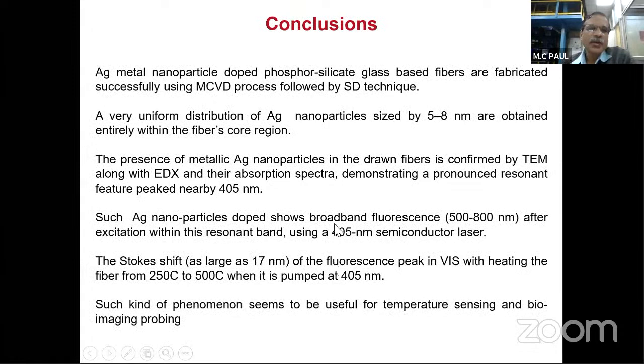In conclusion, for the silver nanoparticle doped fiber, we have made phosphosilicate glass by MCVD, modified chemical vapor deposition, followed by the solution doping technique. We have maintained uniform silver nanoparticles of 5 to 8 nanometer along the whole diameter of the core. The presence of silver nanoparticles in the drawn fiber is confirmed from EDX, and the absorption spectra give rise to a plasmon resonance absorption peak at 405 nanometer.